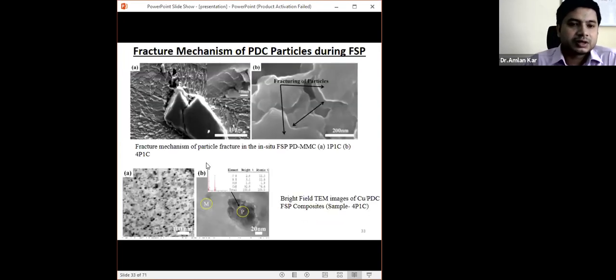So the fracture mechanism we have discussed, we can see here as well. You can see these are the particles which have been consolidated in the matrix, and these are the shear layers. Also we can see that the shear deformations have been taking place on the particles, and because of the shear deformations there is a fracture taking place. And this is the fractured particle. You can see how one particle has been fragmented during the process. This is the TEM image. From there you can see the particles. There are many particles where the particle size is approximately 40 nanometers. So this is an innovative way of fabricating nano-composites.